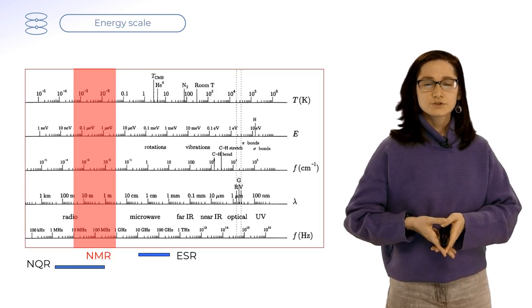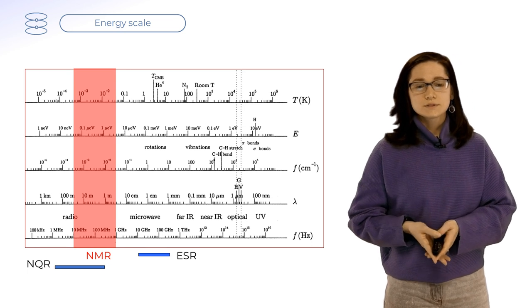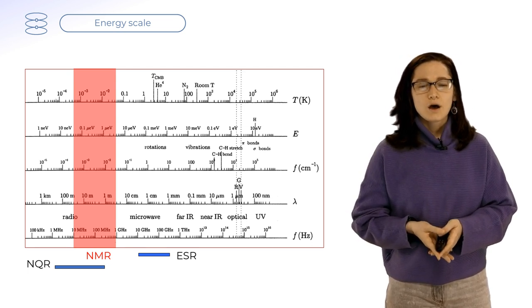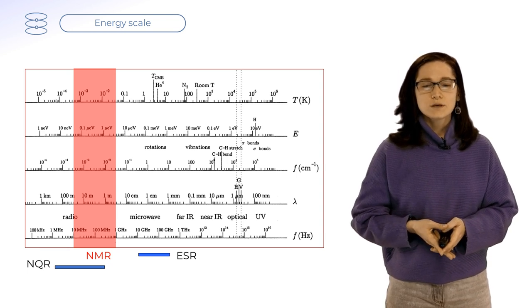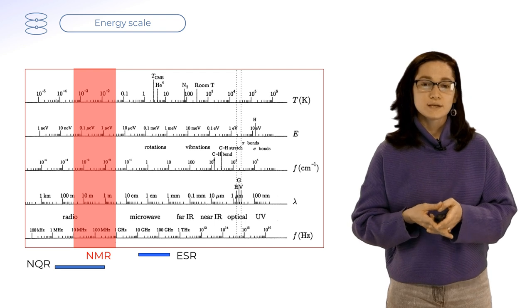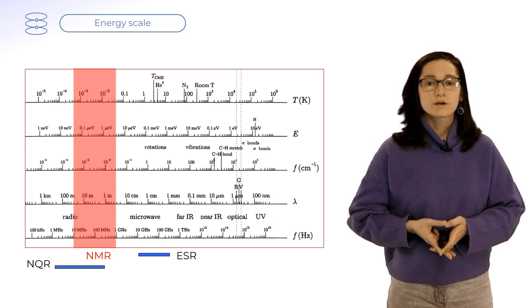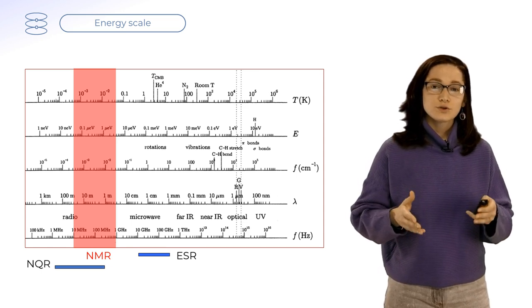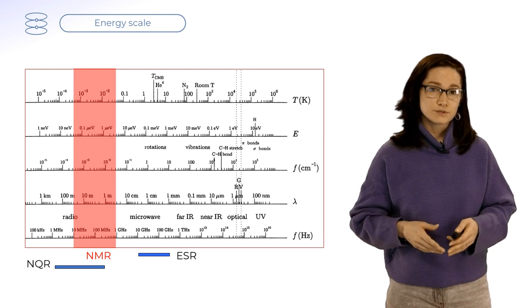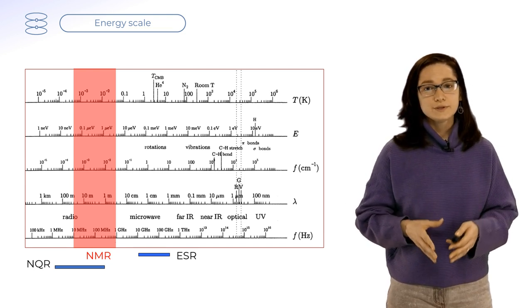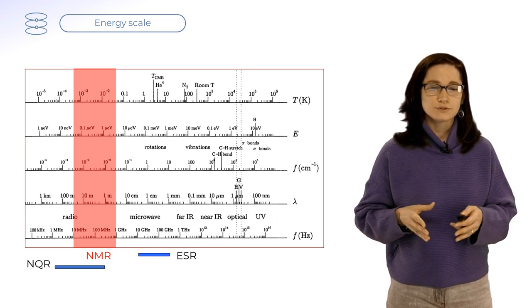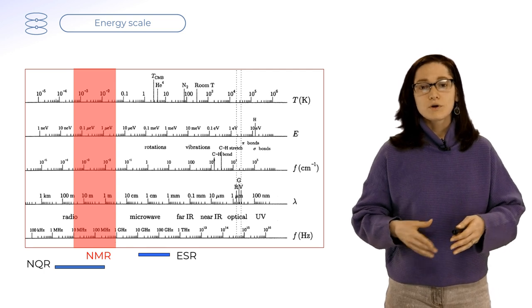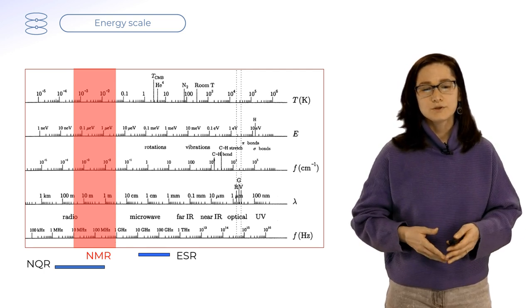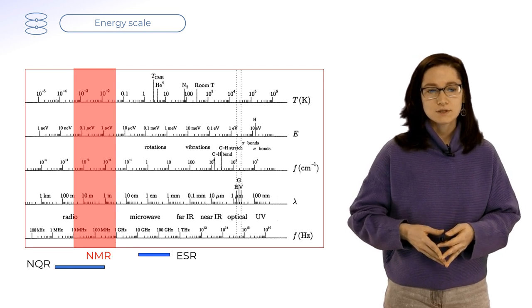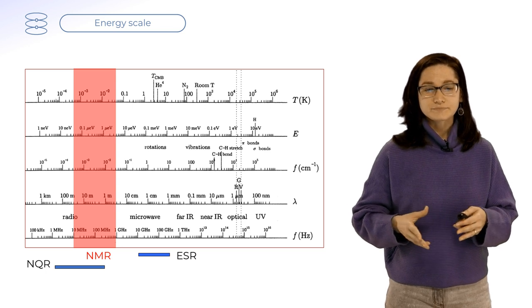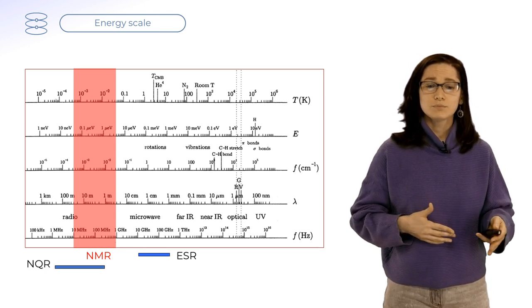This slide shows us a scale of energies and frequencies in various units: kelvins, electron volts, inverse centimeters, hertz. The red stripe marks the region from approximately 10 megahertz to 1 gigahertz. It is the region where NMR is observed. Here you can see that the region where NQR is observed is a little bigger, but it also includes the region of NMR observation. So it interferes a bit and changes the picture of the spectrum. The upper limit of the NMR observation is determined instrumentally by the magnitude of the magnetic fields of existing superconducting magnets, and can be shifted upward somehow, for example, using pulsed fields.